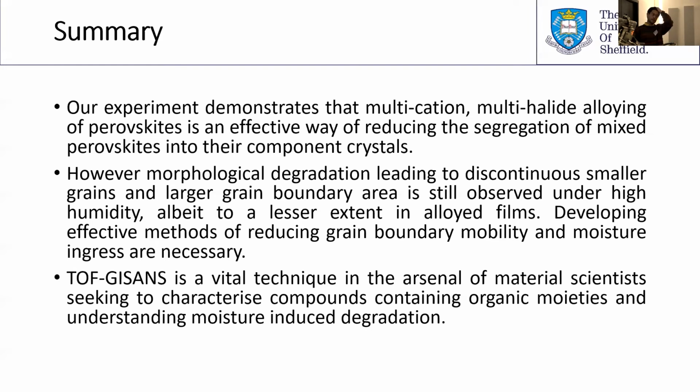No, I mean, if you calculate the tolerance factors, once you get into these multiple anion cation systems, they're not as obvious as you might think. It doesn't go that cubic, I would have thought. Well, yeah, it is better than MAPI, at least. Sure. I'm genuinely interested because we find exactly when we have these triple cation mixed anion cells, the activation energy for ion motion goes through the roof. It's higher than anything we've measured on any other component systems. What is it about that mixed anion cation system in particular that is just so much more stable? It's an interesting question. I'm not sure I know the answer to, but yeah.